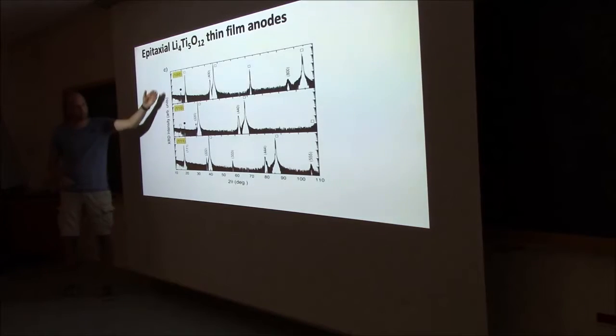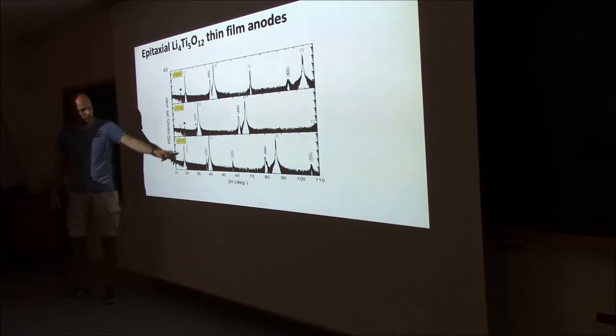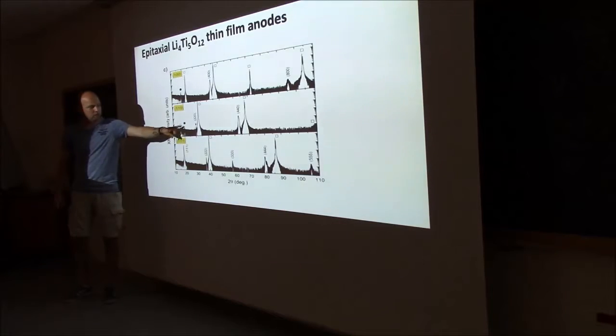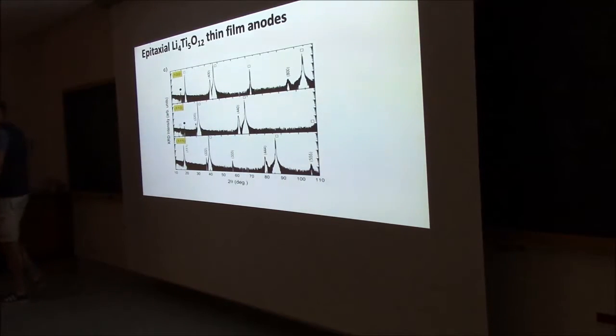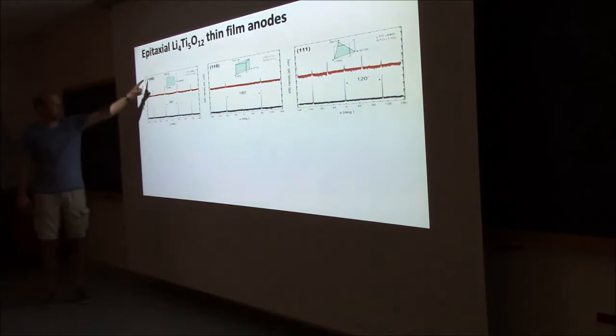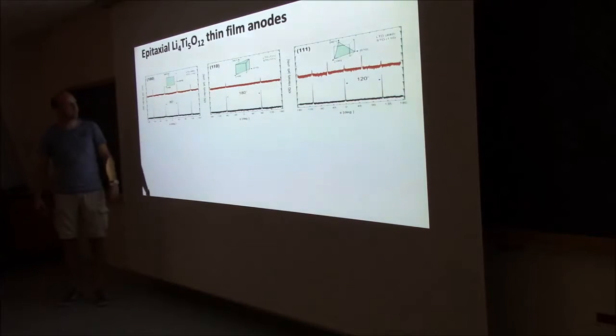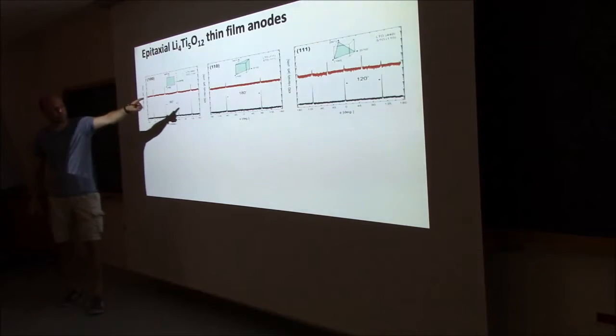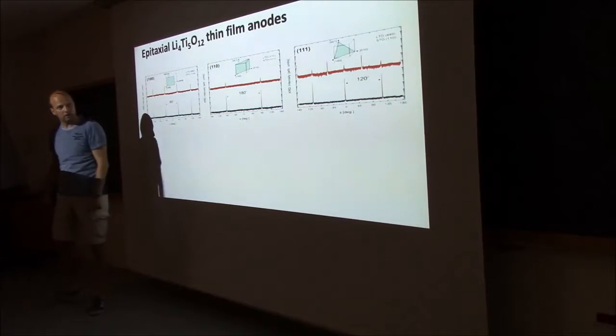Similar as before, we grow these films, 3 different orientations. You can see that they are following the orientation of the substrate, with only a few minor peaks of some minor phases which are indicating that there is no, or there's a deficiency in lithium. If you look how those phases are aligned on an STO substrate, the 100, you can see the 4 peaks, so it's nicely aligned with the substrate in plane orientations. 110, the 180 peaks, and there on the 111 you can see it's also with the same peaks, but you can see there's a doubling of the peaks. There are 2 options in which those rectangles or those triangles are rotated.